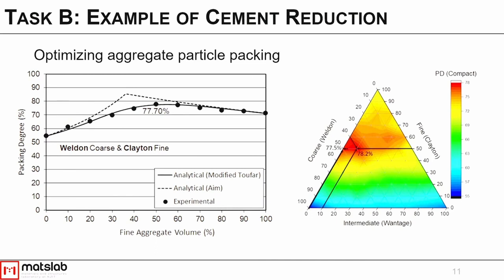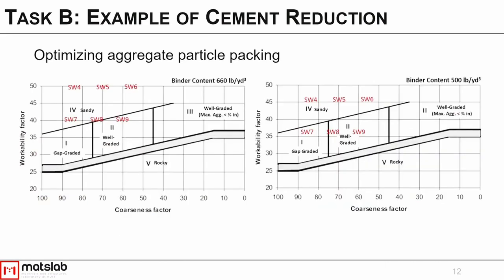So for example, these two aggregates, we were able to get a 77% void space filling with just two aggregates, but when we moved up and included a third aggregate, we were able to improve that by another 0.5%. So that's all space that we were not having to put cement in.